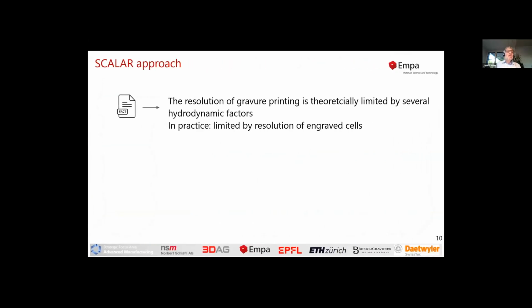The approach in our project was digging in the literature. Conclusion number 1 is you cannot go to infinitely high resolution with gravure printing because you're limited by several hydrodynamic factors. But in practice, gravure printing today is limited by the resolution of the engraving itself. In the graphic arts industry, this is typically done by electromechanical etching, so you do not need very high resolution. 20, 30, 40 microns are enough. What you can do today is direct laser engraving of the cylinder that goes down to resolutions of 4 micrometers. What you want to have at gravure printing is to go somewhat lower.